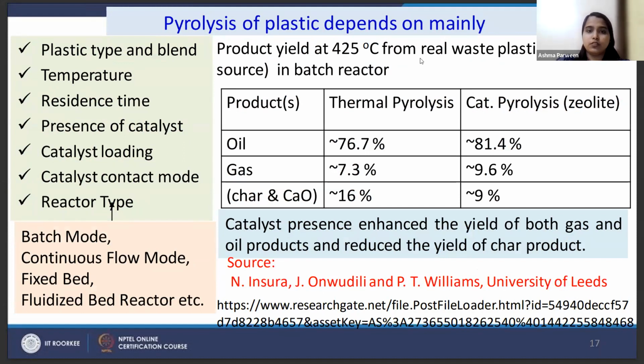Here is an example, product yield at 425 degrees centigrade from real waste plastics in a batch reactor. Here we can see that if we are using thermal pyrolysis, then we are getting 76.7% of oil. And if we are using catalytic pyrolysis with zeolite as the catalyst, then the oil yield has increased from 76.7% to 81.4%. And gas has also increased from 7.3% to 9.6%, but the solid content, char, has reduced from 16 to 9%. So our goal is also to improve the content of liquid, that is oil, after pyrolysis. Catalytic pyrolysis gives better fuel as compared to thermal pyrolysis.